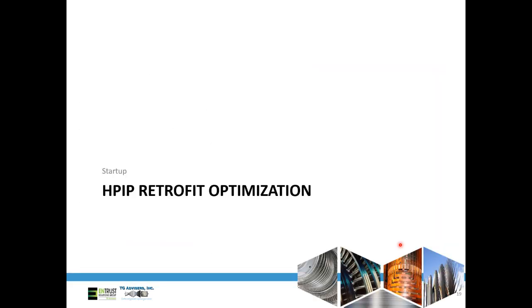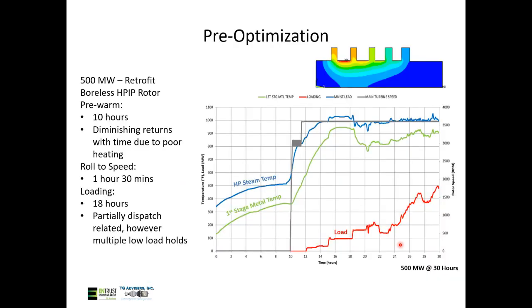So here's an example of an HPIP retrofit optimization. Really, the takeaway on this one is going to be the pre-warm period. Depending on the OEM and the vintage, you may have a process called pre-warm by pressurization, or pre-warming. What this does is pulse in steam. We can't just admit significant steam into the casing because then the turbine is going to roll off gear. So we just pull steam in and get this slow, gradual heating over time. The problem is if you follow this process to the T, you often end up with a very slow process.